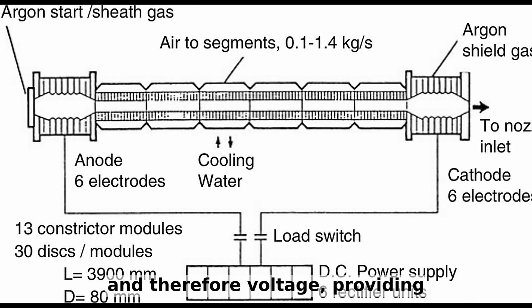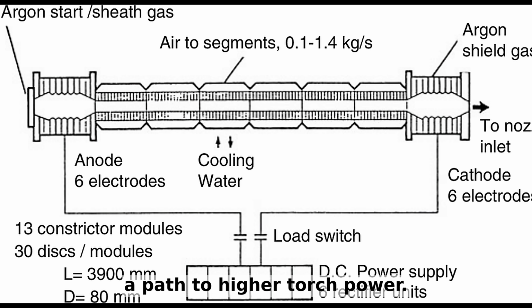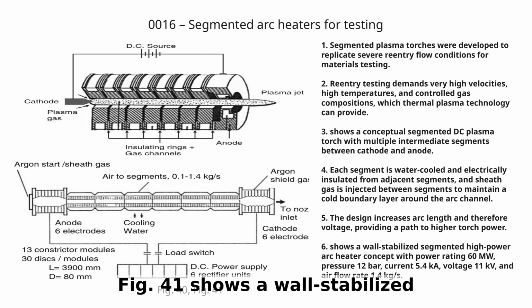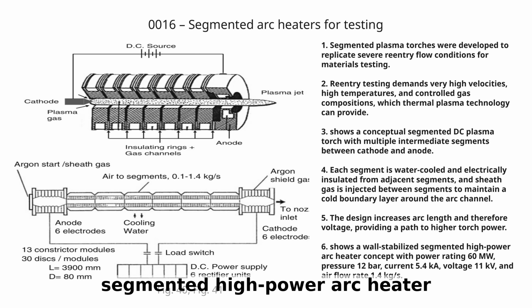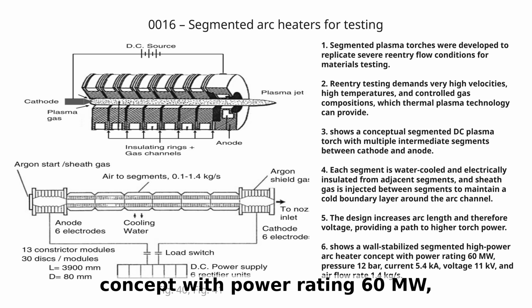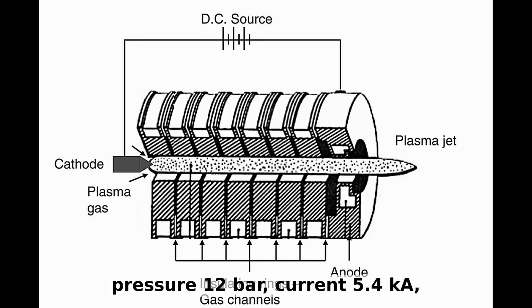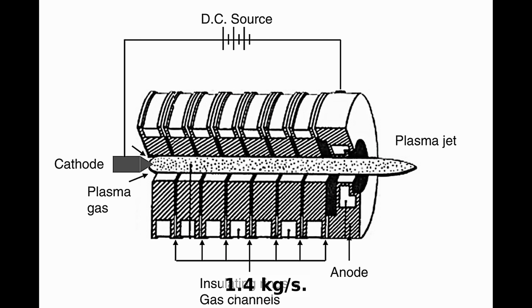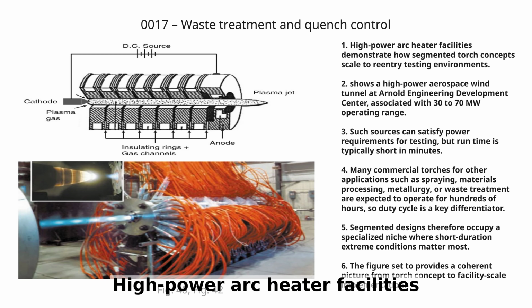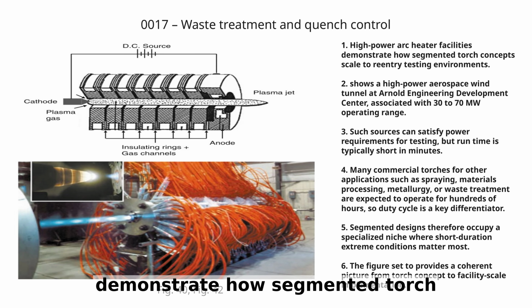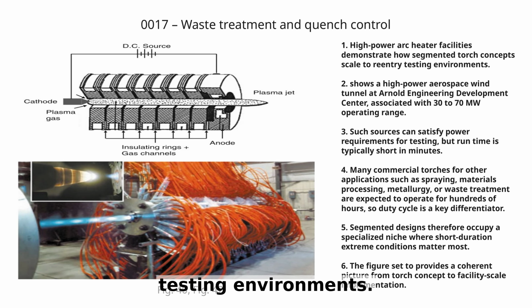The design increases arc length and therefore voltage, providing a path to higher torch power. Figure 41 shows a wall-stabilized segmented high-power arc heater concept with power rating 60 megawatts, pressure 12 bar, current 5.4 kiloamperes, voltage 11 kilovolts, and airflow rate 1.4 kilograms per second. High-power arc heater facilities demonstrate how segmented torch concepts scale to reentry testing environments.